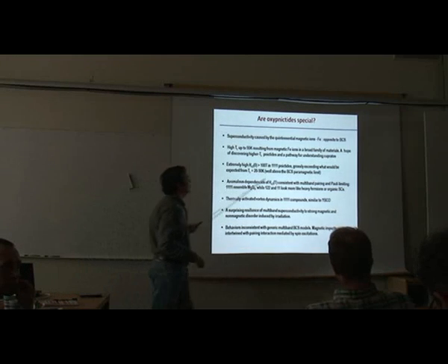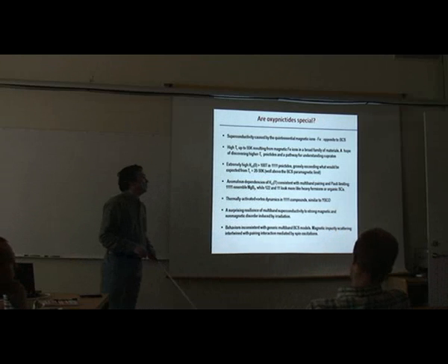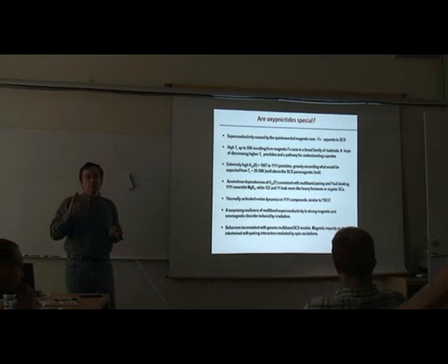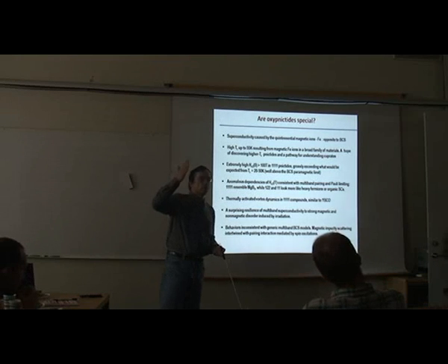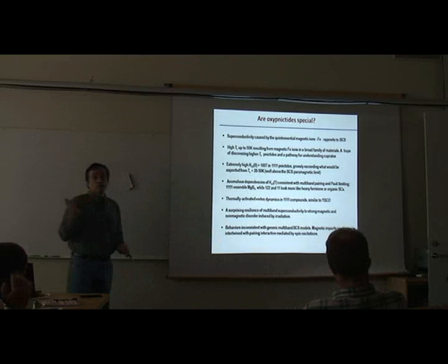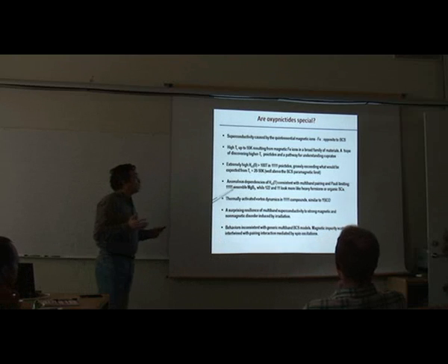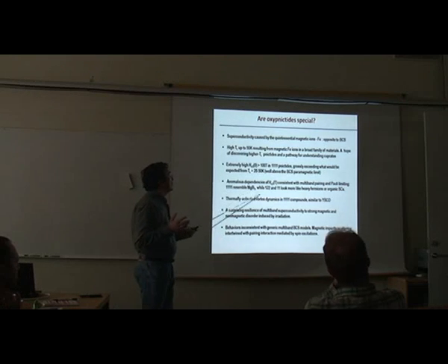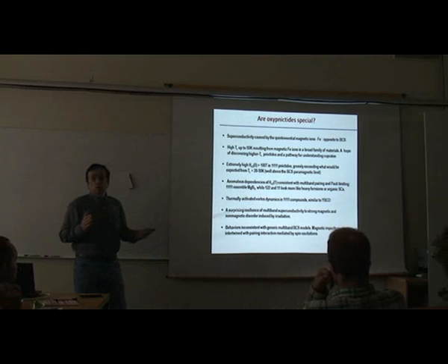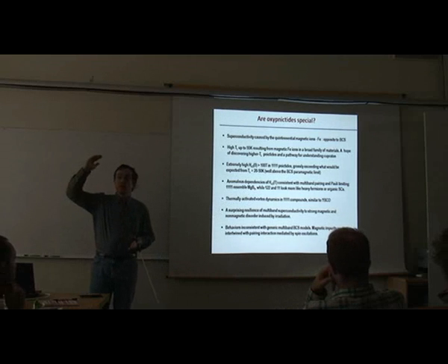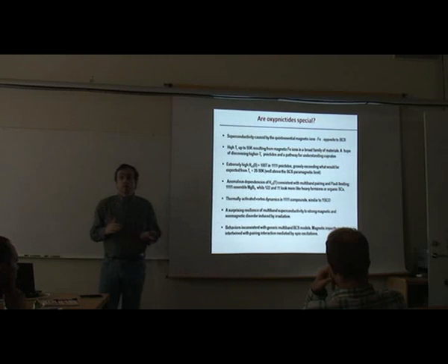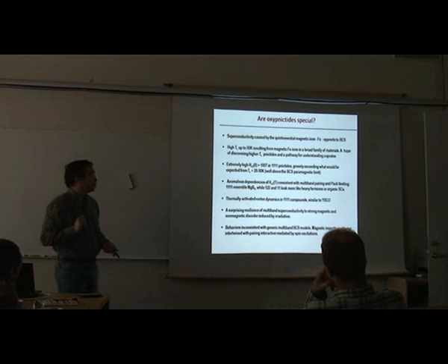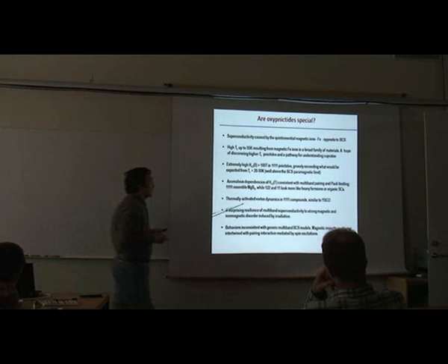So then what's unusual, the temperature dependence of the upper critical field is very anomalous. It has nothing like you would expect from a conventional superconductor. It has a strong upward curvature in some materials. In some materials it doesn't. In some materials it looks more like a conventional two-band superconductor like MgB2 with upper critical fields maybe 5-6 times higher. The scale is just larger. Or in some of them it looks more like heavy fermion HC2 with a very distinct shape, and I'll talk about that too.